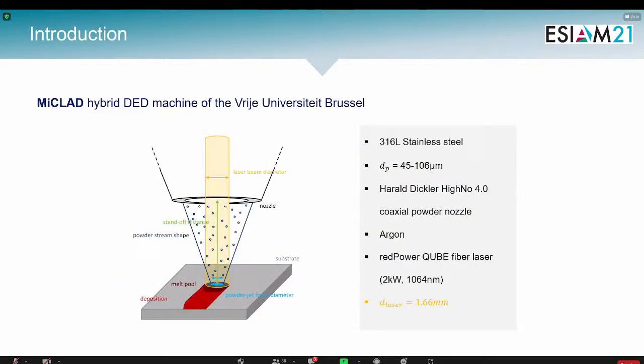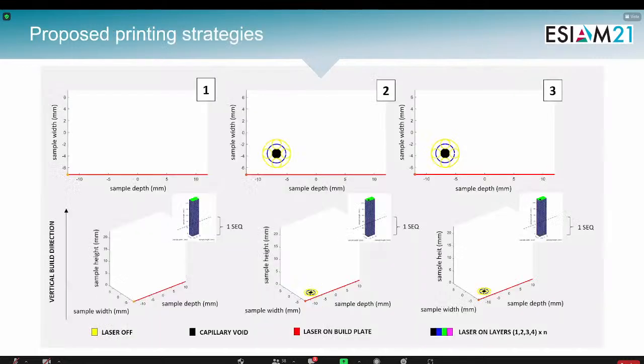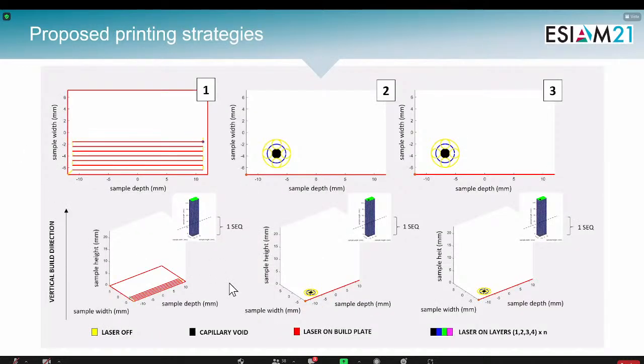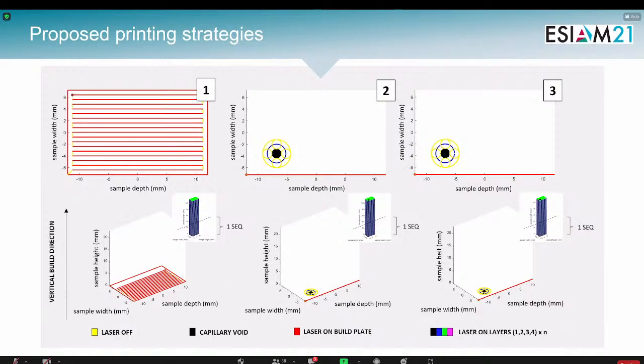So for the printing of the samples, 316L stainless steel was used, and argon was used as shielding and carrier gas, and our melt pool size is around 1.66 millimeters. I give a short overview here. So 3 printing strategies were proposed. They all rely on a vertical build-up direction of the sample, as you can see here.